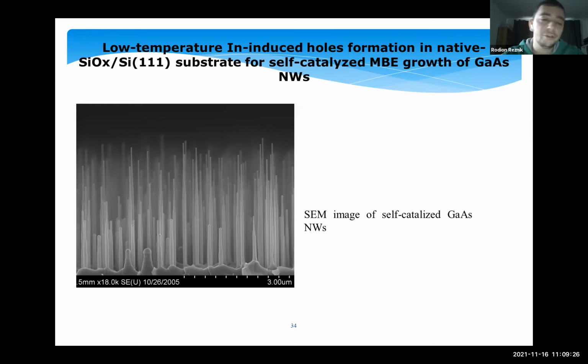I mean, homogeneous in terms of diameters and length of nanowires, using some special procedures, for example, like etching the native silicon oxide layer by gallium droplets, and then forming gallium droplets again in these holes and growing nanowires, like some cheap analog of lithography maybe. But to evaporate the gallium from the substrate, we have to increase the temperature of the substrate significantly, which is critically important for silicon technology, as I told before.